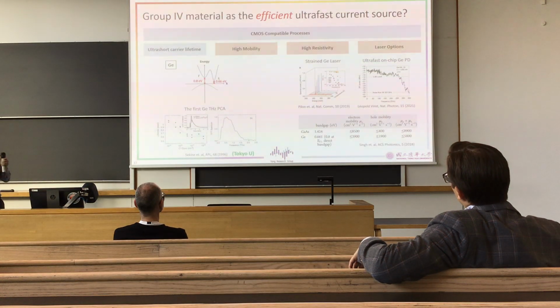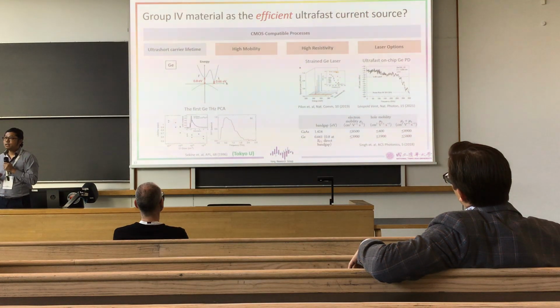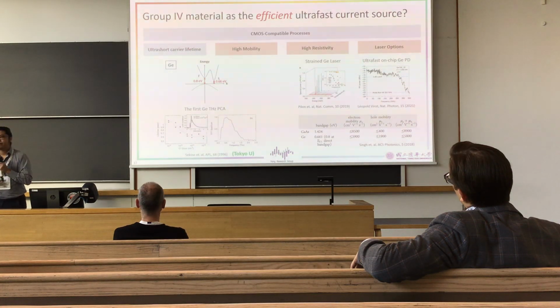Actually, when we checked, we found that in 1996, the first germanium terahertz PCA was developed at the University of Tokyo. They used ions to bombard the germanium surface to create short carrier lifetimes, making it a short carrier lifetime material, and they had decent performance and a decent bandwidth. In these 30 years, because the semiconductor industry grew so fast and so big, the germanium growth process is very, very mature, so you can have even comparable carrier mobility to the III-V materials.